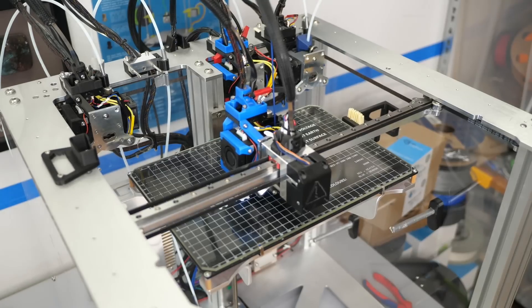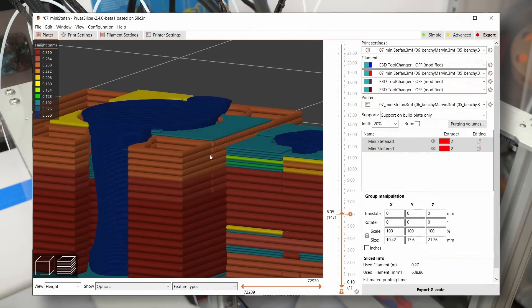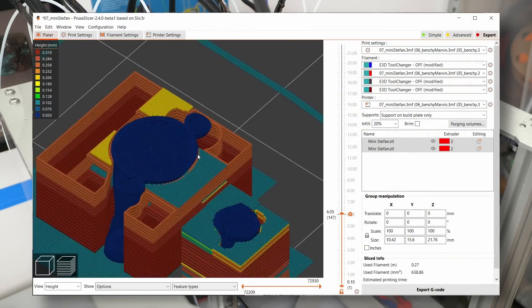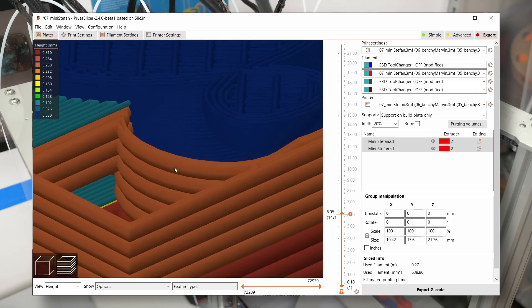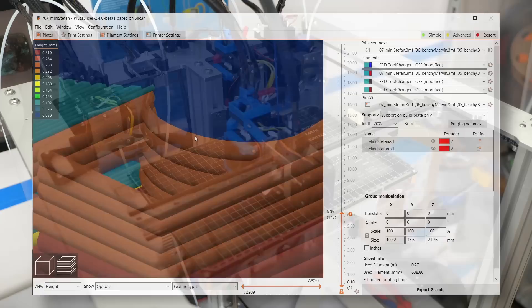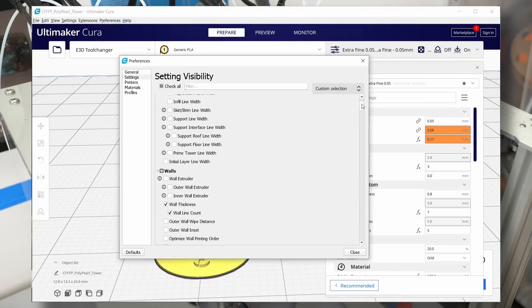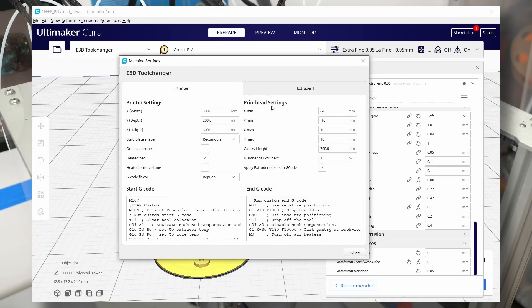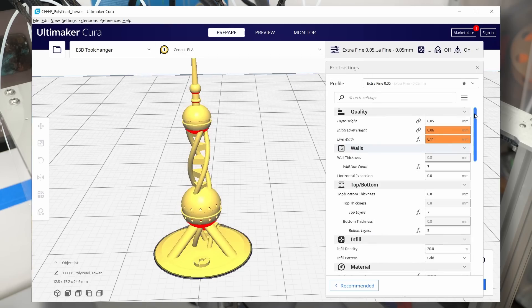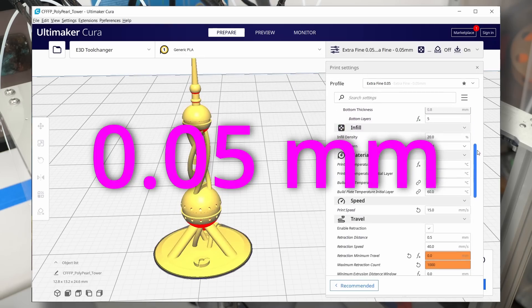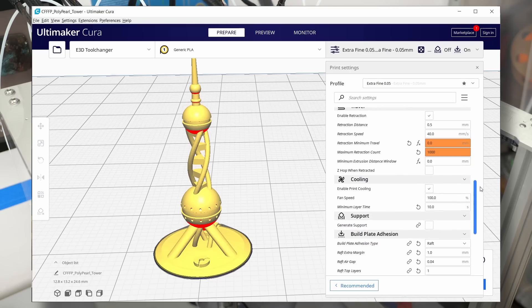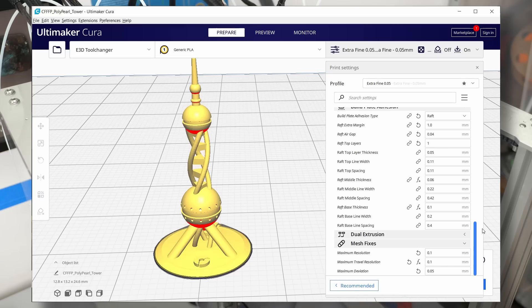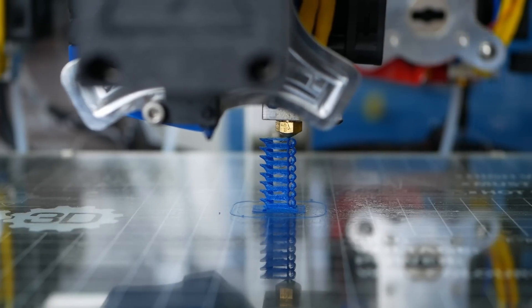I first tried to use PrusaSlicer to create a printing profile but later switched to Cura. PrusaSlicer seems to have some hard-coded settings that make support structures and rafts a pain to use at this scale. Cura gave me all the options and enabled me to create a profile without real issues. I set the nozzle diameter and then adjusted extrusion width and layer height accordingly. I printed all of the parts at 0.05mm layer height, which is 50% of the nozzle diameter and used an extrusion width of 0.11mm. I reduced printing speeds to only 10-15mm a second and printed my tiniest temperature tower so far.